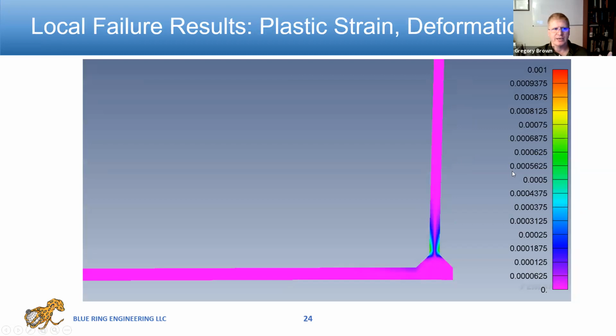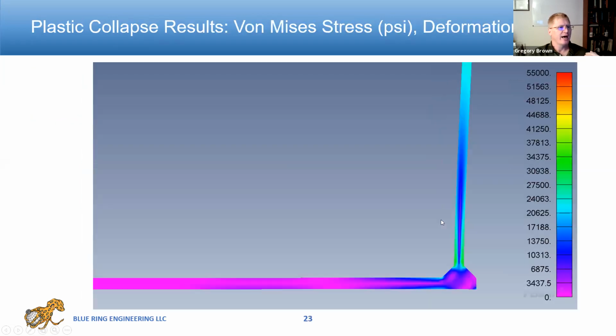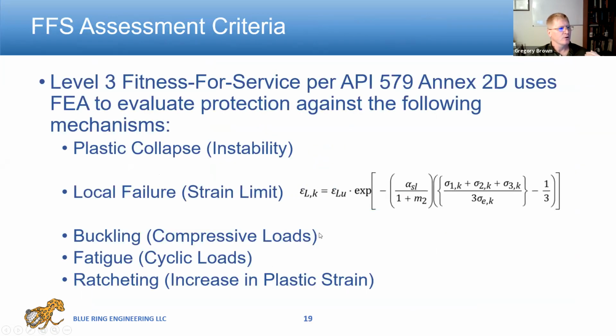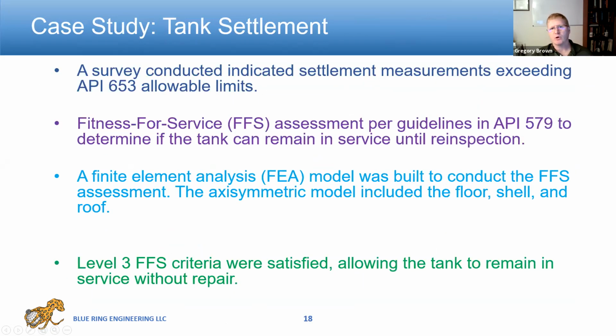Local failure, you're looking at plastic strain, how much non-recoverable deformation you have. And in this case, this is the plastic strain plotted. And we are actually getting, again, plasticity occurring at that location, but it wasn't so significant that it did not meet API 579 limits. So the result of that was that it met all the requirements. So that tank could stay in service. They did not have to repair the floor of that tank.